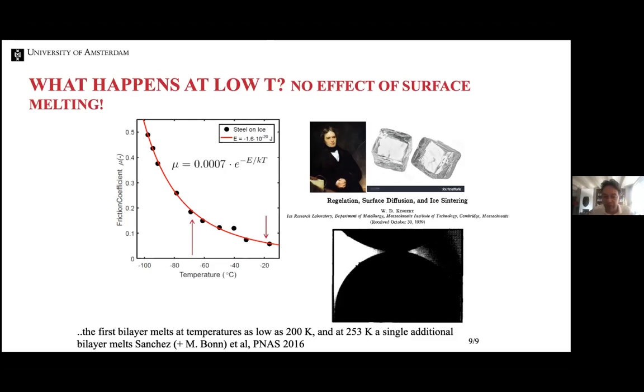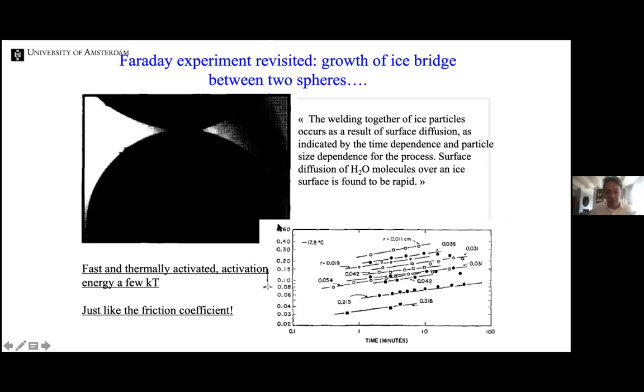However, as many people have forgotten, this experiment was later done quantitatively by Professor Kingery from MIT, who was a ceramics professor actually, and so the ceramics people are very interested in sintering. And so he did this with 2 ice spheres and looked at how the neck between the 2 spheres actually grew. And so here you get the neck radius as a function of time, and you see that instead of going linearly as one would expect if there would be a layer of liquid water, the slope is actually much, much smaller. It's actually a slope of 1/7 is what Kingery found for the radius as a function of time on a log-log scale.